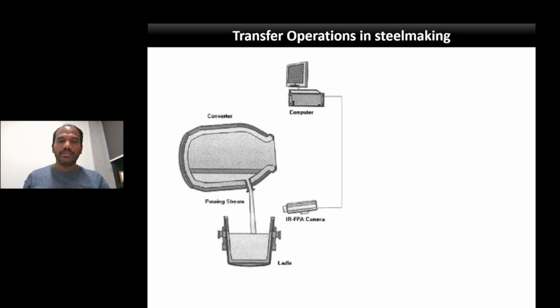So, moving into the topic, we can see transfer operations are very important in the steel making. So, there are several places that transfer operations take place. We can see transfer of liquid steel from BOF converter to ladle, also transfer of liquid steel from electric arc furnace to ladle, which is named as tapping process. This takes place at the primary steel making section. As soon as the crude steel is produced, the tapping operation will be taking place to transfer the liquid metal from one vessel to another vessel.